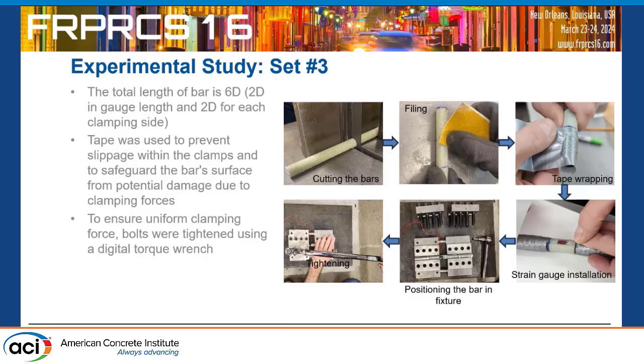So here's just a quick process of how these things are done: cutting with a bandsaw, applying strain gauges. We did a couple of trial and error. We realized that we need to provide a little bit of cushioning at the end, so we use duct tape, of course. So we use duct tape at the ends. We found it very, very useful. Of course, it has been tightened with the hand wrenching system. We put steel bars at the end, so the FRP bar doesn't go all the way. It's from this point to this point.